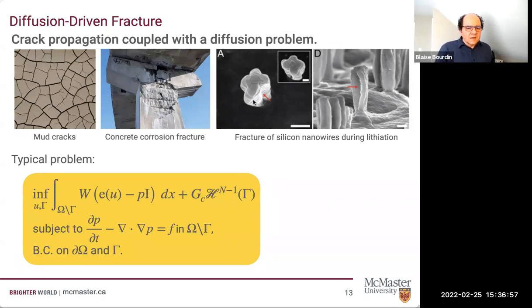So these are little cylinders that swell for some mechanism that I don't understand in the battery, but in doing so, they observe a generation of cracks. So again, here, an abstract version of that would be to introduce a diffusive field P that, for instance, would solve a classical diffusion equation, but in a domain that depends on the crack, and then account for it.